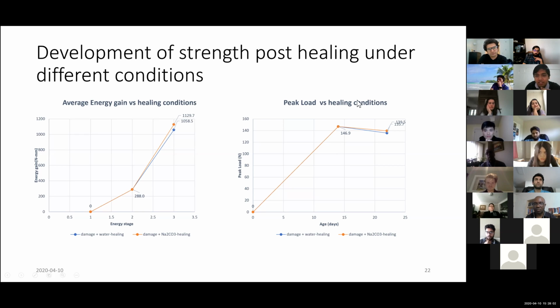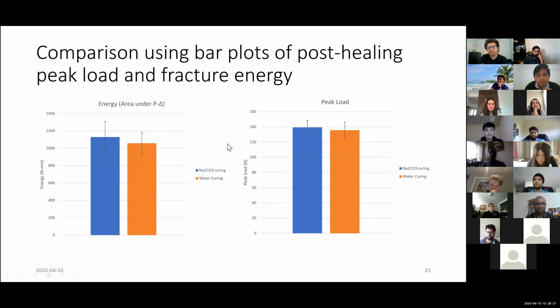And then in terms of peak load, we can see that even though the sodium carbonate is performing better than water, the overall peak load is never recovered, since once the adhesive bond is broken and it's now weaker in bond, you can never really gain back that sort of adhesive bond between a fiber and concrete specimen. So this is the same graph again, just the final values of peak load and fracture energy, so as to demonstrate that sodium carbonate is slightly performing better, but there is not much of a significant difference in this case that we can conclude anything from.